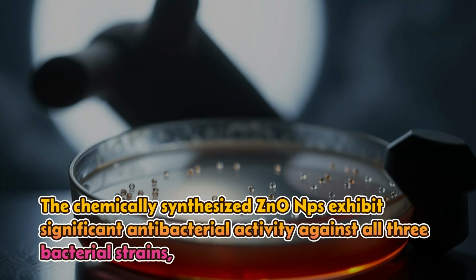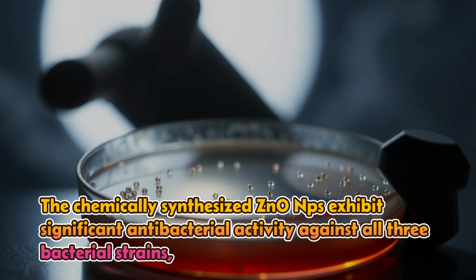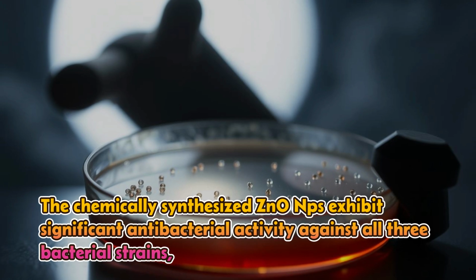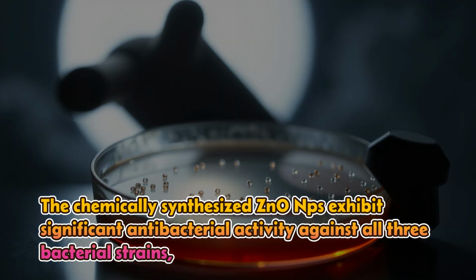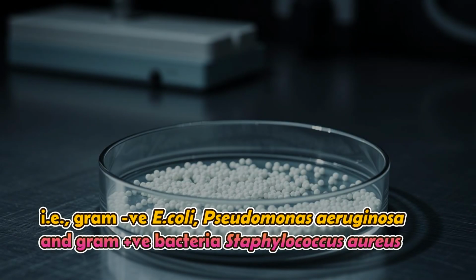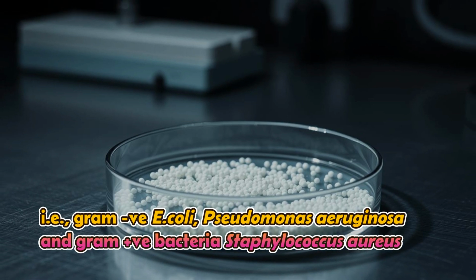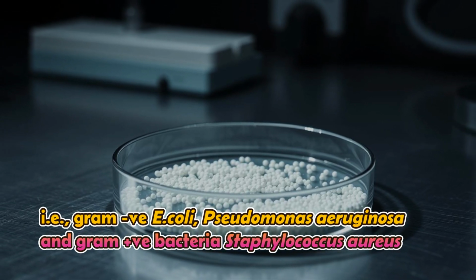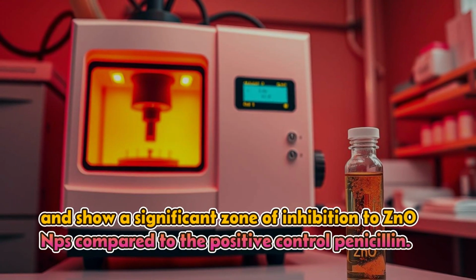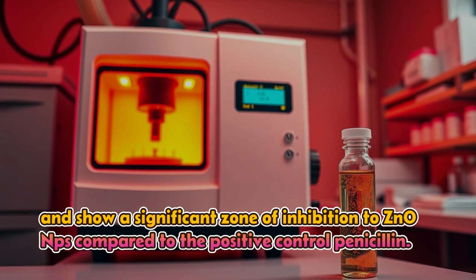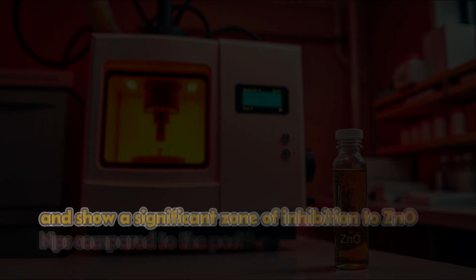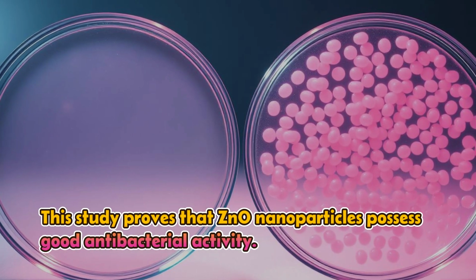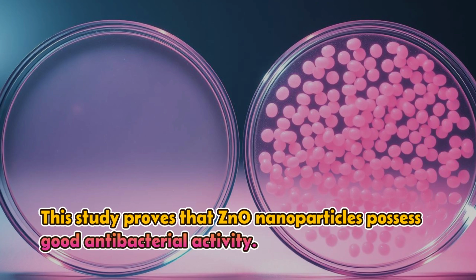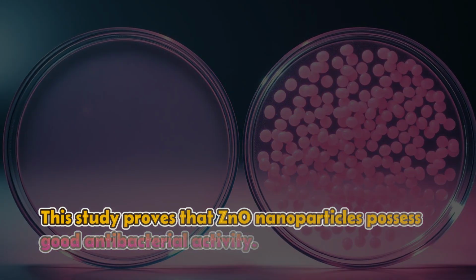The chemically synthesized ZnO NPs exhibit significant antibacterial activity against all three bacterial strains, i.e., Gram-negative E. coli, Pseudomonas aeruginosa and Gram-positive bacteria Staphylococcus aureus, and show a significant zone of inhibition for ZnO NPs compared to the positive control penicillin. This study proves that ZnO nanoparticles possess good antibacterial activity.